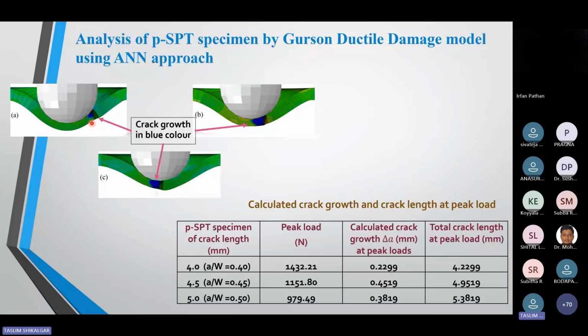So again, I wrote one small code to get this. I provided all these numerical node as well as element data to find out the crack growth, and with the help of this code I calculated the crack growth in each specimen at the peak load only. This is the crack growth observed in each specimen with the help of these damage mechanics models. I then added the initial crack length, so this is my final total crack length observed at the peak load.